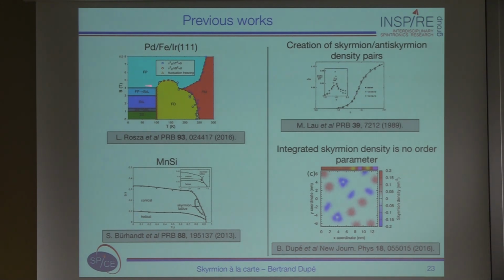That surprises us a lot, especially when we look at this kind of phase diagram for manganese silicon, where this feature is not found. You can have a pocket, but here there is no 90-degree angle to be found between the phases. So that's this work in comparison to the other phase diagram.